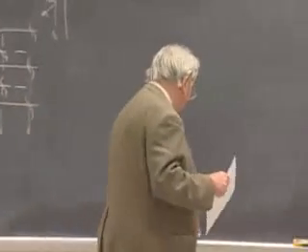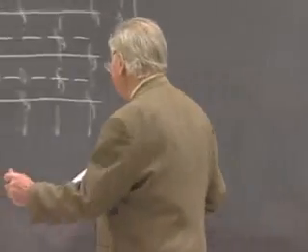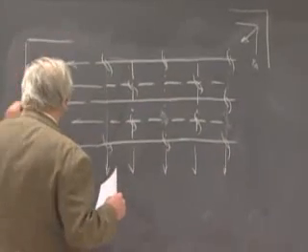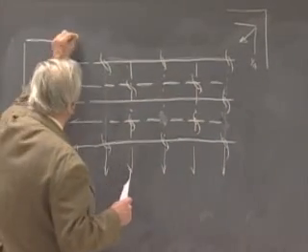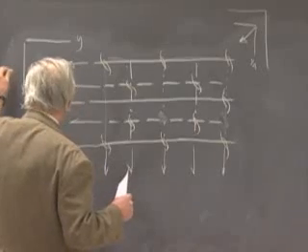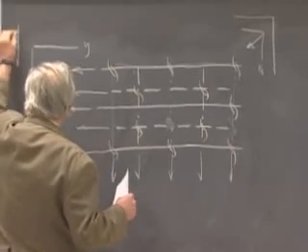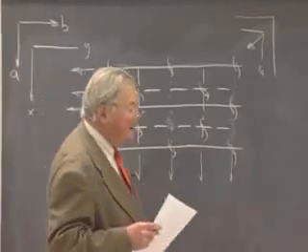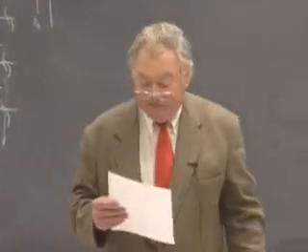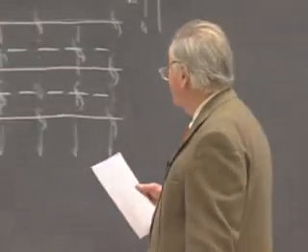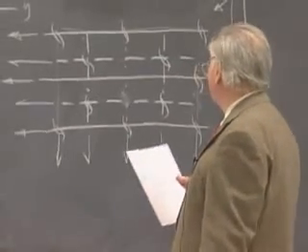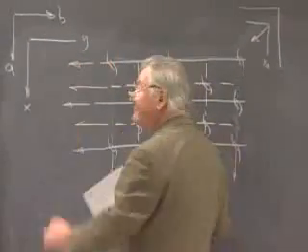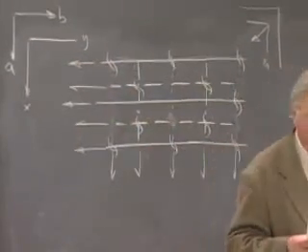Something, again, that is nowhere stated but always assumed is that the origin, the two variables x and y, or the axes a and b, are assumed to run from upper left to lower left for a and the coordinate x, and from upper left to upper right for the axis b, and therefore plus c comes out normal to the plane of the projection.